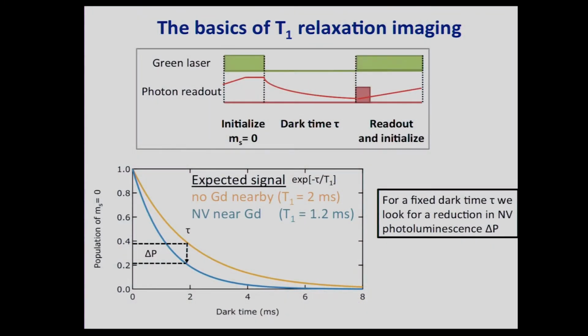I already mentioned that the way gadolinium works is when it comes near to, say, a proton spin, in our case the NV, it causes the NV to relax more rapidly. And so the way we do the experiment is, here's the time scale, the chronology of what happens in our experiment. We turn a green laser on. By shining a green laser onto the NV, we can initialize, we have, again, this two-level spin system. We can initialize our spin into one of the two levels.